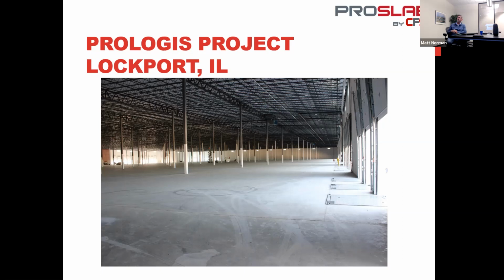You should expect on these wide slab floors to get much wider joints than you would normally get. What we try to do is control the shrinkage of the mix by specifying a 0.04% shrinkage number or less based on the ASTM C157 test. So we will do shrinkage testing before to confirm the mix design meets that. And at the same time, what you're going to want to do is